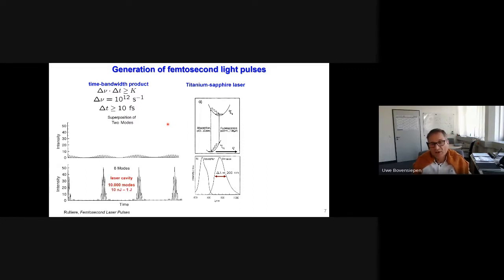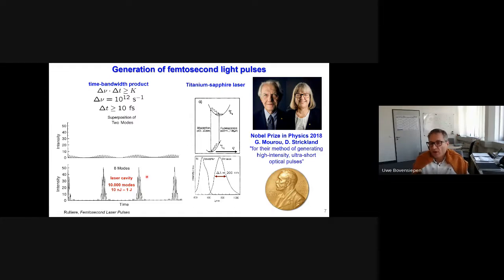But now we have to realize this in a laser cavity. And a laser cavity can typically maintain several thousand to 10,000 modes, so it's sufficient to really provide the bandwidths and get femtosecond laser pulses. If you do this in a simple cavity, you work with energies per pulse of several nanojoules, but with amplifier schemes, you can get up to a joule or even more. And for this amplification, Gérard Mourou and Donna Strickland, the pioneers who have investigated this and introduced this amplification, got the Nobel Prize in Physics in 2018 for their method of generating high-intensity, ultra-short optical laser pulses. And we stand on the shoulders of those giants and exploit this in our research.